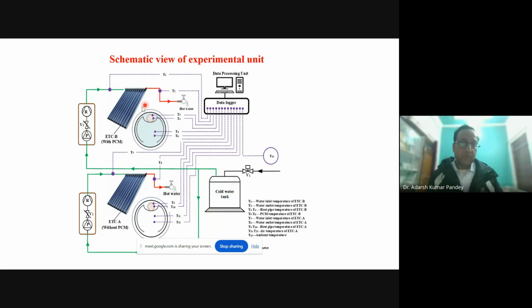But what we have done is we have utilized the hollow space of the evacuated tube, and we inserted the heat pipe into these evacuated tube collectors, and we flow the water through the heat pipes. Because now water is going through the heat pipe, we have a remaining space. We utilize this remaining space and insert phase change materials into it. So you get the flow of water through the evacuated tube, through the heat pipe, and this space is filled by the phase change materials, and these phase change materials get charged when the water is flowing in the daytime.